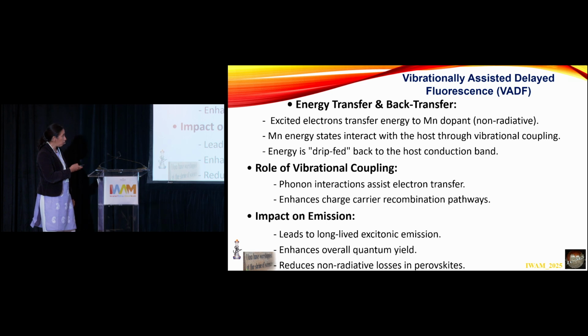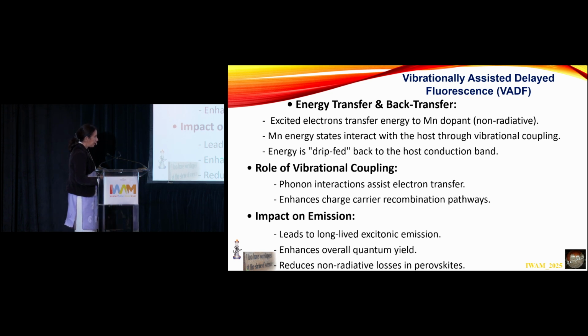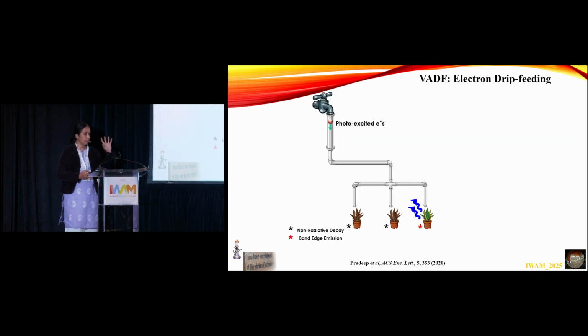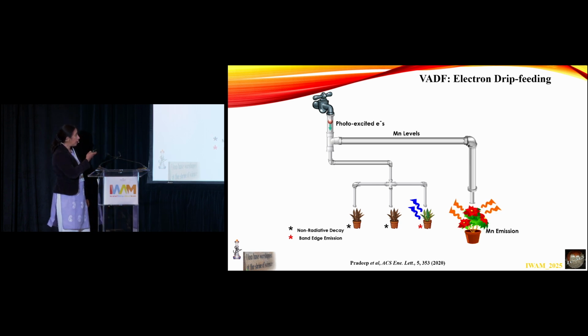So what is the role of vibrational coupling? Here there are phonon interactions that assist electron transfer and enhance the charge carrier recombination pathways. If this is true, what is the impact on emission? It leads to long-lived excitonic emission, enhances the overall quantum yield, and reduces the non-radiative pathways. So in a nutshell, if I were to summarize this pictorially, as soon as I excite a few photoelectrons, instead of going through the normal path, the manganese level comes in and picks it up very quickly.